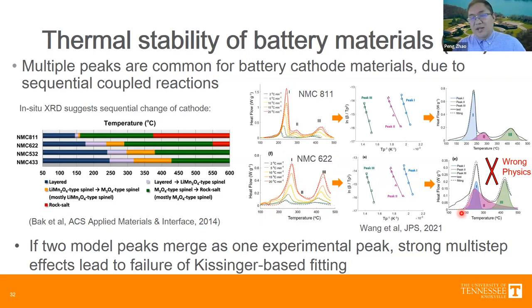For example, your reaction two even occurs before reaction one, which is not even possible because everything should start from reaction one that follows the first type spinel, and then the first type spinel becomes a second type, and then eventually becomes rock salt. So if we apply the Kissinger method to battery material in general, especially when there are overlapped peaks, we can have the wrong physics and misleading results, even if eventually the fitting agrees with the experiment.